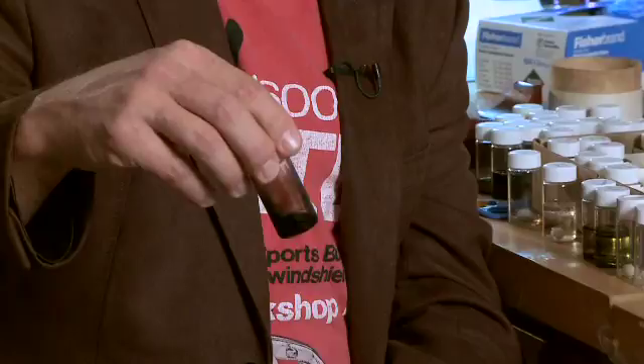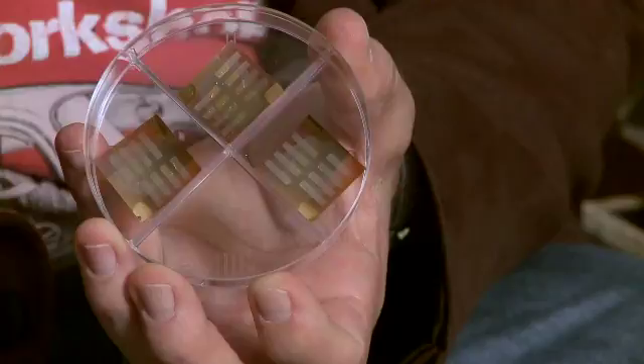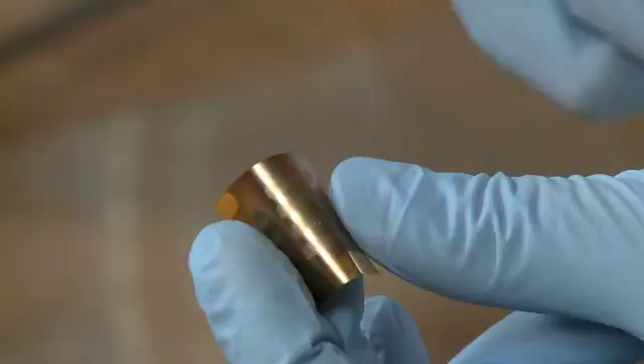These are nanocrystals suspended in a solvent. You take this material and you can deposit it as you would in ink. These are actual test devices made of the solar ink deposited on plastic. These are devices that are sandwiches where you have the metal contact on the bottom and metal contact on the top to extract the charge out.